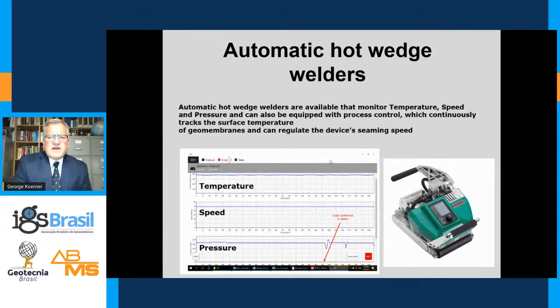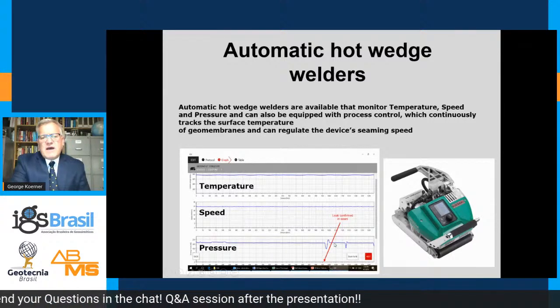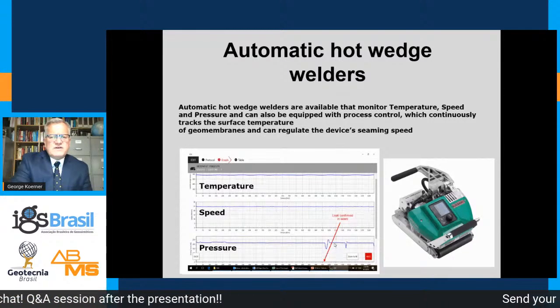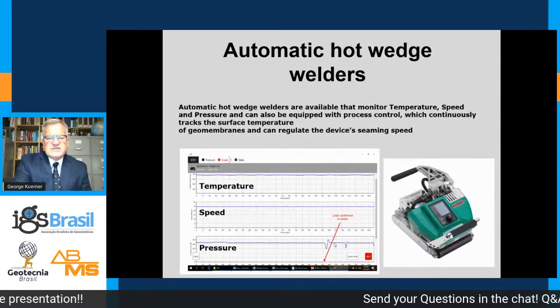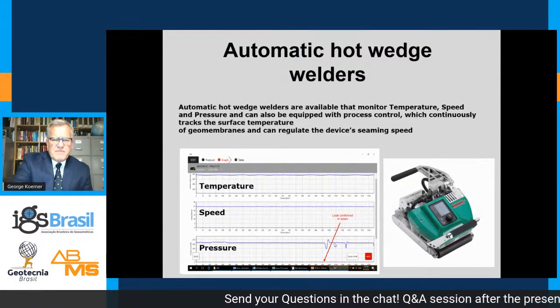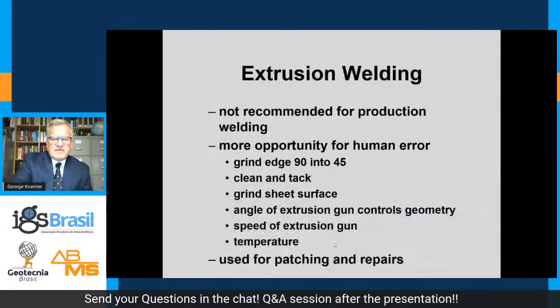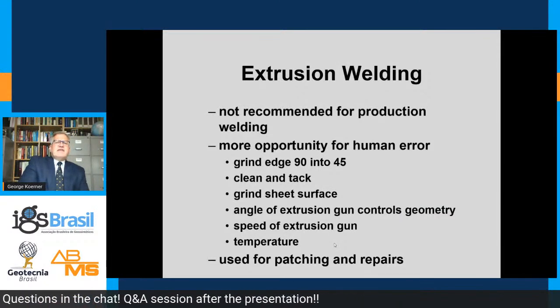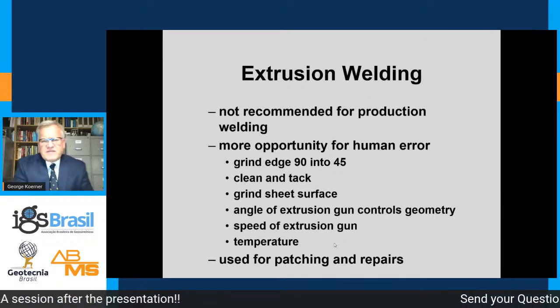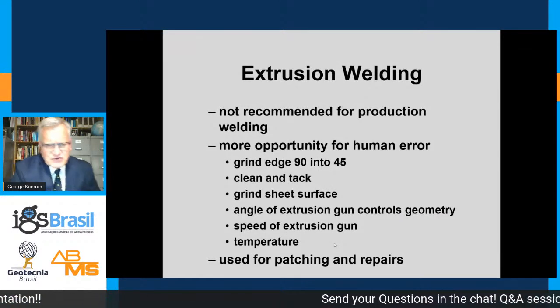These are now fully automated hot wedge welders. This automated welder or smart welder can record temperature, speed, and pressure. Any anomaly to this can be recorded, and then the QA personnel can focus on those locations where these metrics are not within threshold. That's wedge welding, very different fusion welding than extrusion welding.